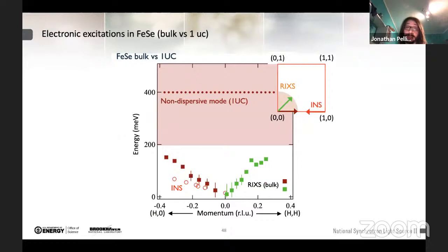Now I want to summarize this experimental evidence in this plot where I'm showing the spin excitations measured for the bulk here, and the non-dispersive flat mode for the one unit cell material, which is hardened and has lost any resemblance of a dispersion. Now, the origin of this peak could be due to different types of excitation.